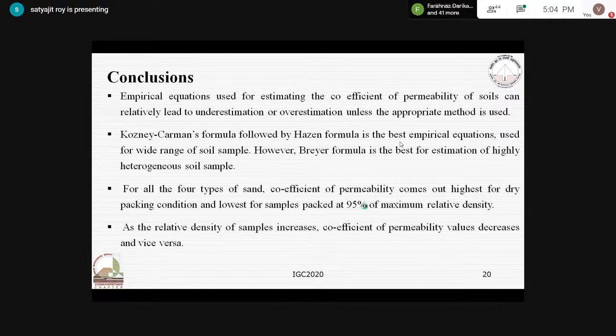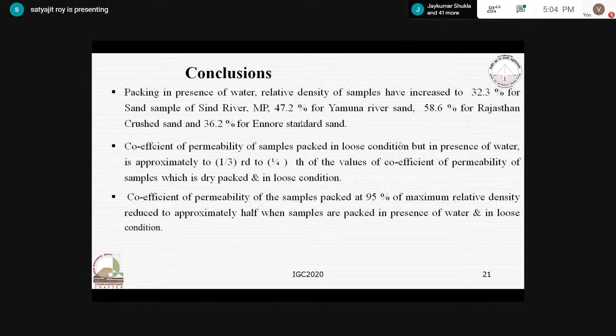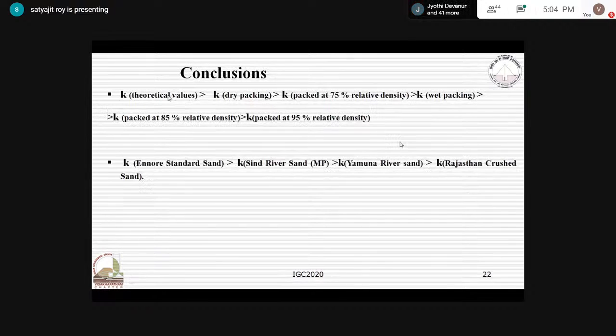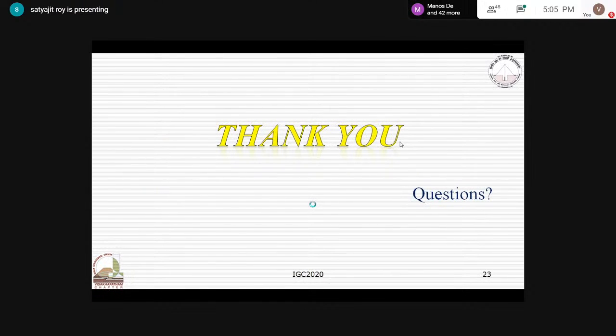Factors affecting permeability: for theoretical, Cu and D10 are more important, and for laboratory, percentage of silt, degree of saturation, and packing are more important. This is my conclusion. Kozeny-Carman is the best for 1, 3, and 4, and 95% relative density has given the lowest permeability values, and the relative density increased in the presence of water. This is the final trend: the theoretical permeability has the highest values, and 95% relative density has the lowest value. Thank you.